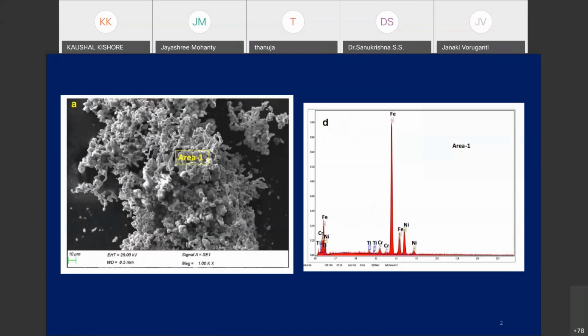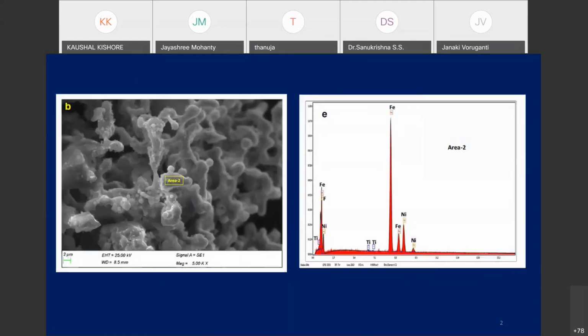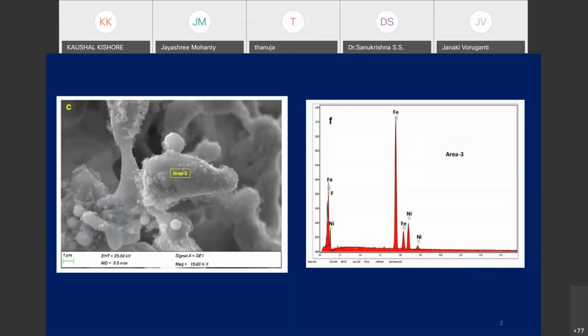Again, we have characterized the material by SEM or EDS, and the area analysis was carried out, and we found that it contains mostly Fe. Iron is the major material, followed by nickel, chromium, titanium, which are also present. So different area analyses we have carried out, and in most of the cases we are getting FeNi, so we thought that it is mostly a FeNi alloy containing some amount of titanium and chromium.